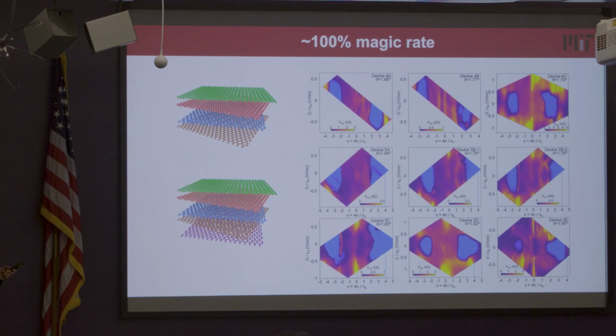I don't see many features. Still, somehow the superlattice fan is just emanating to a single point. So I think that's okay. But how accurate it is to assign 2, 3, 4 exactly by dividing that region into 4 might have a little bit more trickiness, because already in the twisted trilayer, the region where the Landau fan from the half filling factor goes is not exactly half of where the nu equal to plus minus 4 goes.